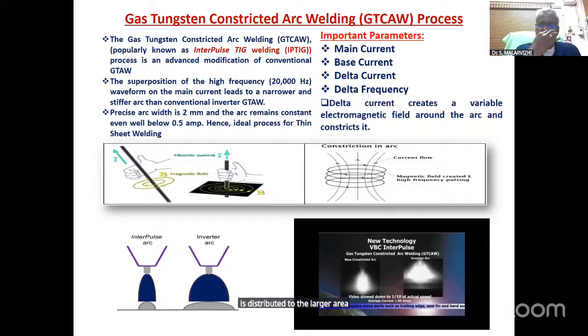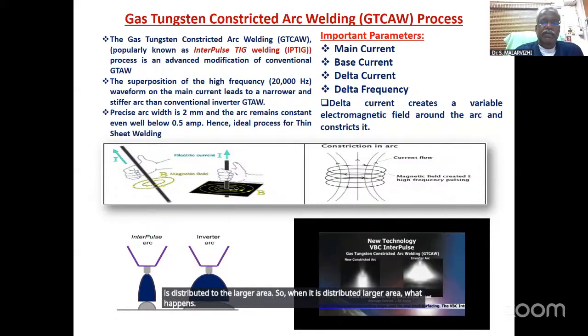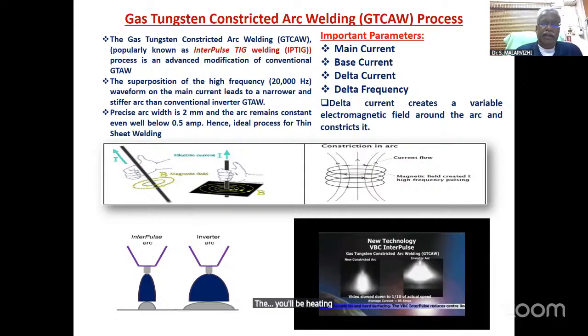So when it is distributed over a larger area, what happens? You will be heating a larger area, and the net result is shallow penetration. But if you are able to constrict the arc by some means, then the arc can be narrowed down and becomes a stiff arc. Once it becomes a narrow arc, the area under the arc is greatly reduced, and you will get deeper penetration in this process. In fusion welding, a process which produces a very narrow weld zone or fusion zone is preferable.